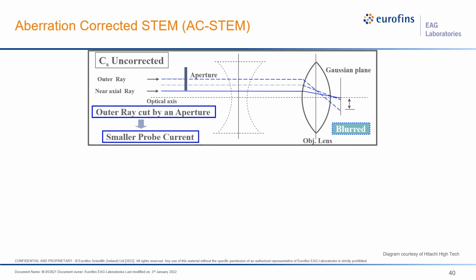And so the next technique that we have to dig further down is aberration corrected STEM, so AC STEM. So the idea behind AC STEM is that effectively the objective lens in the STEM is going to have spherical aberration issues, and so the further away from the optical axis that electrons get in the column, the lens aberrations cause over focusing, and then eventually our final probe will be blurred somewhat because of this aberration. So to optimize it in the past, we've had to use an aperture which effectively cuts off these off-axis electrons, which effectively lowers our probe current. So that makes things a little bit more difficult to get the signal and noise that you need.